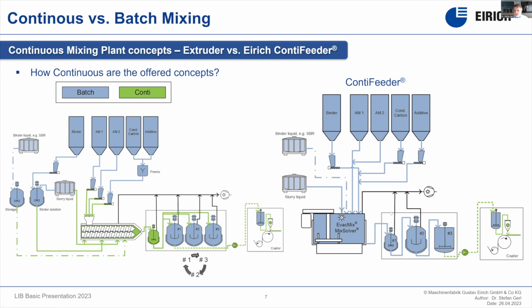And then we go into a series of tanks. Typically, we have one tank which is directly connected to the mixer itself, which has the same volume. By this, we are sucking out the coating slurry with vacuum, and we can qualify it. We can take samples. We can put in these systems with return pipes also additional sensors. And if this batch is qualified by the operator, we are sending it into buffer tanks, which are then connected directly with the coater, so that we have also a continuous supply of the coater, which is the most important part for the customer.